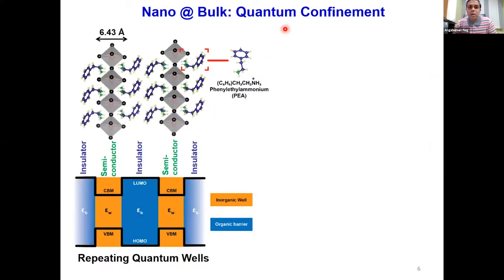And the first observation is the quantum confinement effect, and I'm going back to one of the earlier figures that we discussed. You get an atomically thin inorganic layer, and if you look at the band offsets here, the conduction band minimum of the inorganic layer and the organic layer's LUMO level, you'll see that the electron resides in this inorganic layer. Likewise, the hole also resides in this inorganic layer. So you have the electron and hole residing in an atomically thin layer, and that gives the strong quantum confinement effect. And then you get the layers of inorganic well and organic barrier layer. So you get a repeating quantum well kind of structure in these single crystals.